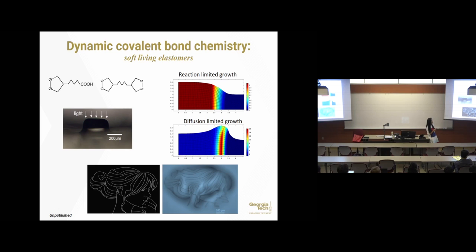So when the reaction is slow and diffusion is fast, you have enough supply of this nutrient, as I like to call it, and so it grows more smoothly. But if the diffusion is slow and the reaction is fast, you don't have enough nutrients supplied to the middle part. It's already polymerized here, grown here. So it grows into a different morphology. So it's really a coupled diffusion, reaction, and deformation problem. And with that knowledge in mind, we can fine-tune this performance.